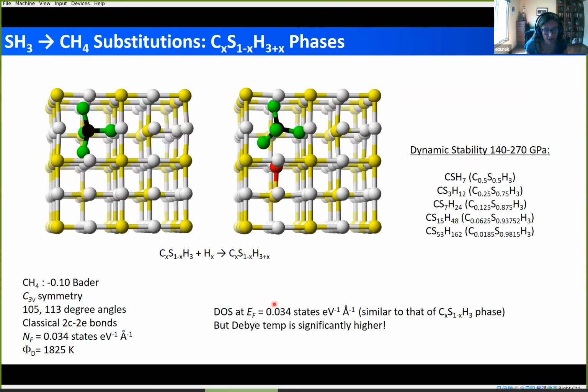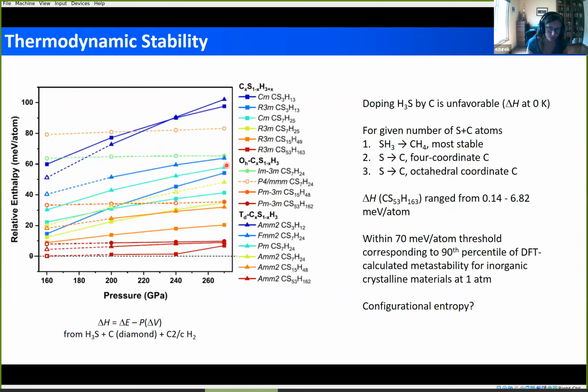However, we do note that adding in this extra hydrogen, because it stretches a number of the sulfur-hydrogen bonds, is going to change the vibrational properties of the lattice substantially. For example, the Debye temperature of this phase is much higher. So it could still have an impact on TC, not through the density of states, but through the vibrational properties.